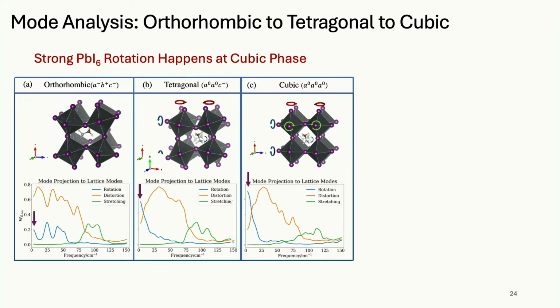But then as you go through the first phase transition to the tetragonal phase, you start to get octahedral rotations around two axes, as illustrated here. And so now for the low frequency part, which turns out to be the most important for the photovoltaic properties, rotation and distortion become competitive. Can you see that? The blue and the orange are almost the same. Then when we get to the highest temperatures, or even room temperature, rotation dominates. So these octahedra are rotating kind of wildly.